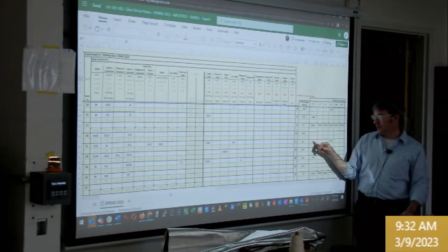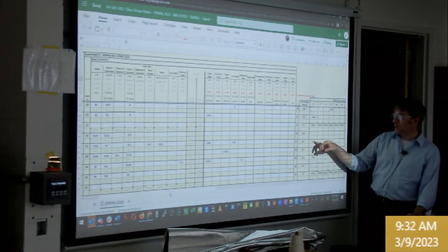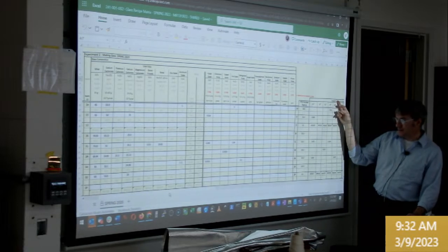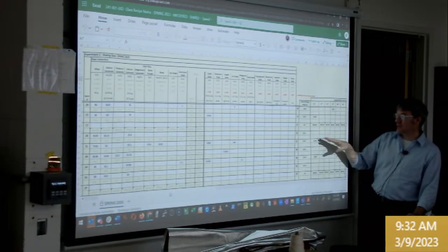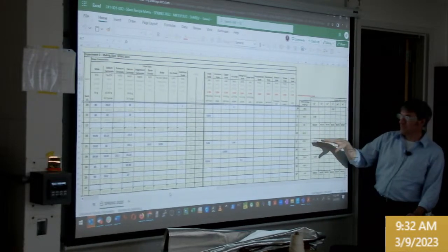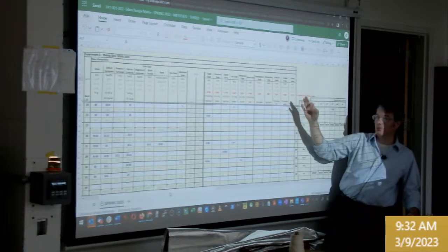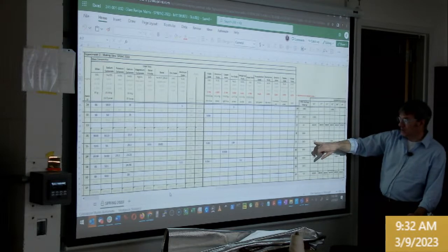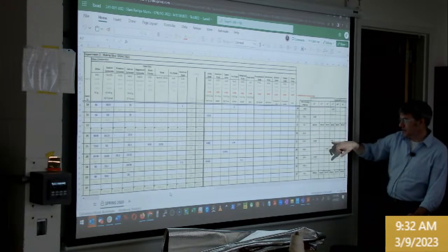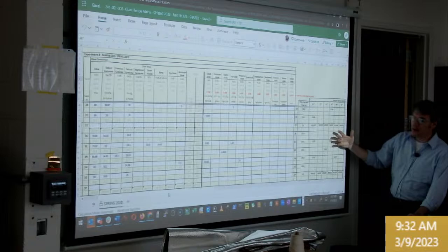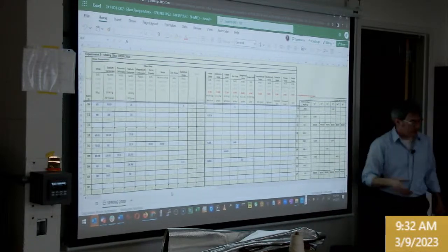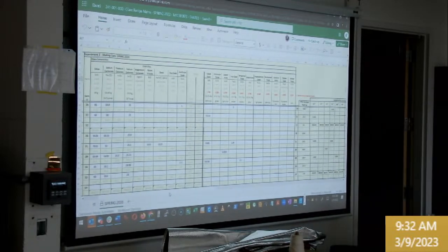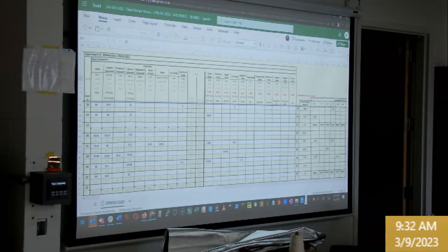That particular batch would be 0.003%. This one is already a percentage, where this one is not; that's a decimal percent. Hopefully that's not overly confusing. But as a percent, 0.003% cobalt and 0.5% iron. Those are the values you would use to describe the color of your batch.